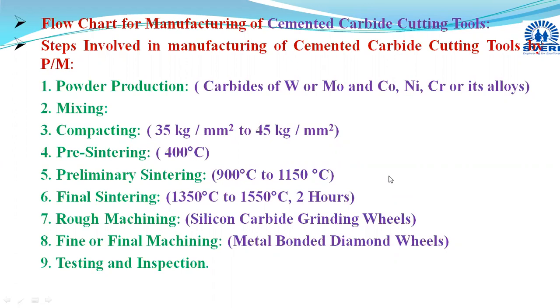So this is taking place in the final sintering, and very large amount of diffusion and changes in the dimensions are occurring in this final sintering due to diffusion of the cobalt. Now here one proper care you have to take: whichever desired shape and size is there, you have to select the component before the compacting or sintering stage. Oversized component you have to manufacture. Then at the final sintering, you will get the approximate shape and size. It's very near to your requirement.